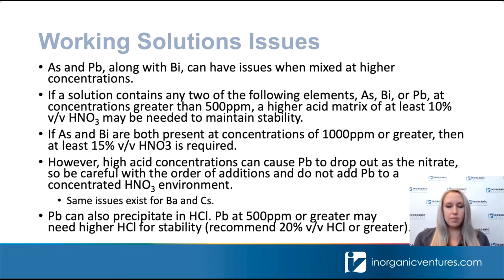But one thing to keep in mind for lead is that if you do have these high acid concentrations, lead can actually precipitate as the nitrate. So you want to make sure that you're manipulating your order of additions and preventing exposure of that lead to really high nitric concentrations. This is the same for barium and cesium as well.